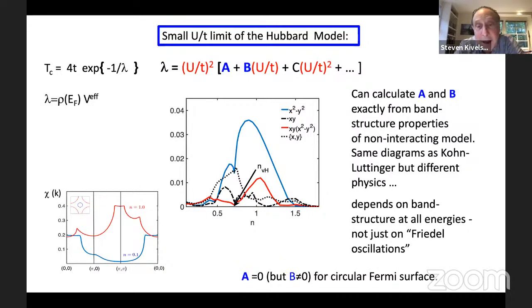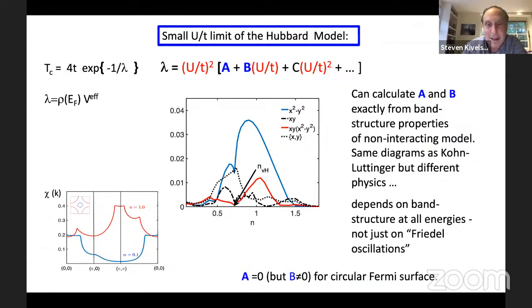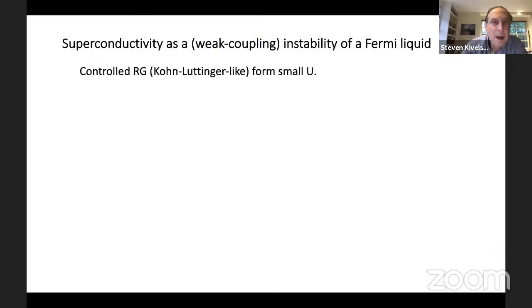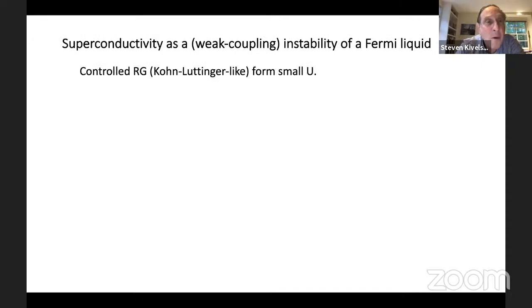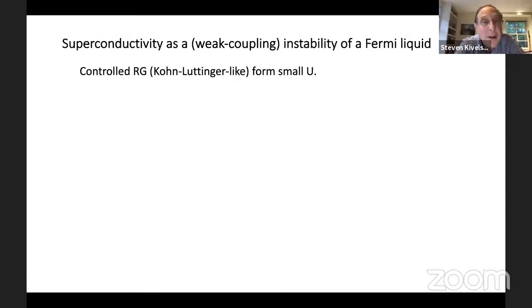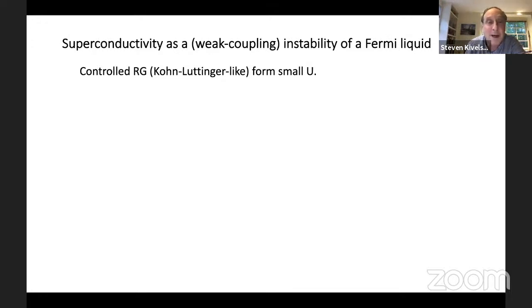In particular, going to the case where N approaches zero — where we have a circular Fermi surface — the leading order term in this expression actually vanishes in two dimensions, despite the fact that there still is a sharp Fermi surface and Friedel oscillations. So we have a way of understanding the origin of D-wave superconductivity from repulsive interactions. We can solve it for the Hubbard model in a controlled Kohn-Luttinger-like way for small U. This explains the origin of D-wave superconductivity and its relation to short-range antiferromagnetic correlations.